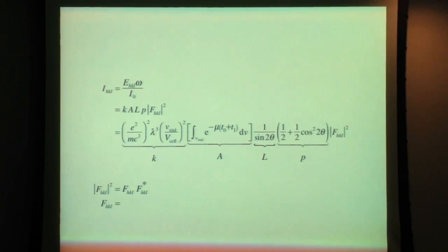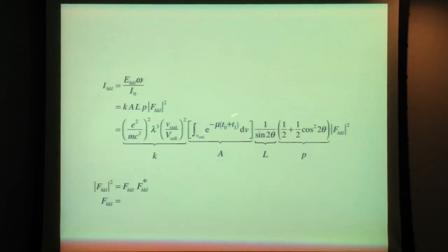We know their values for all the atoms. And then we have to sum over all points in the crystal. That's the tricky part. So what we end up doing is subdividing the crystal in our imagination or in our computer into tiny little blocks, and then do an actual summation rather than an actual integration. Each little block would have a particular volume.